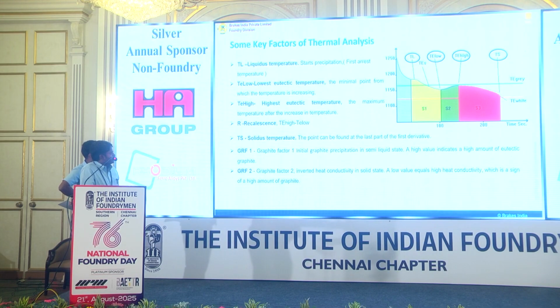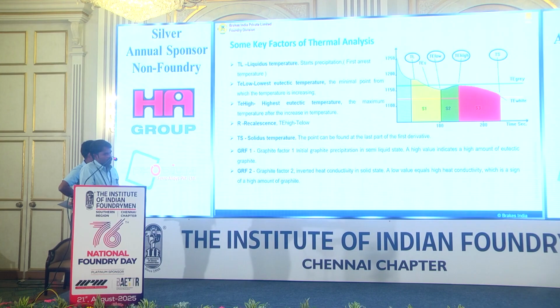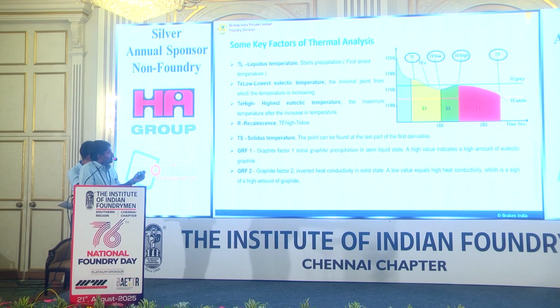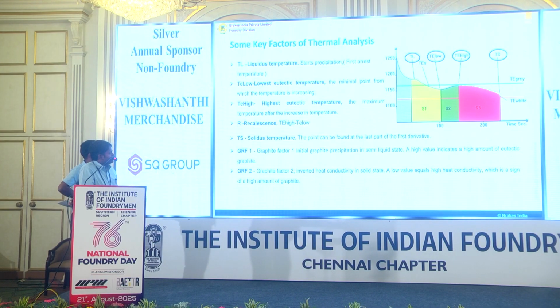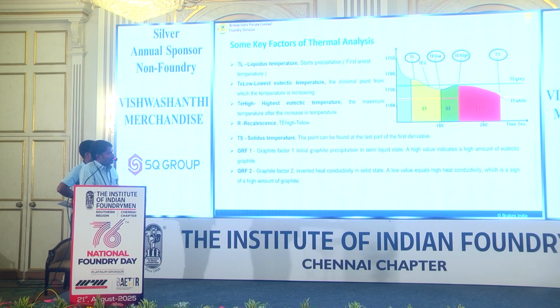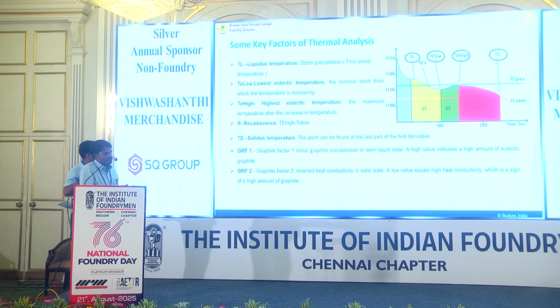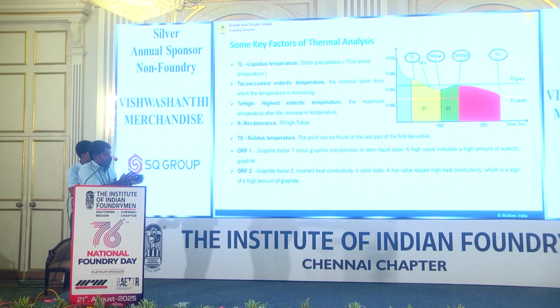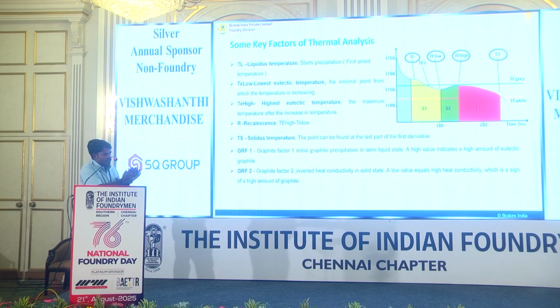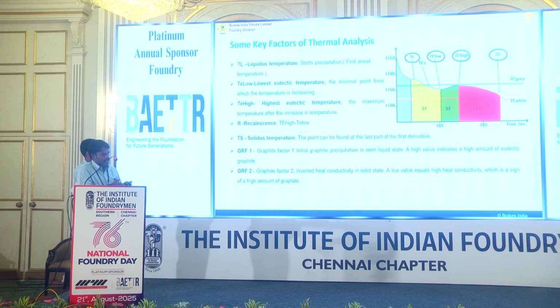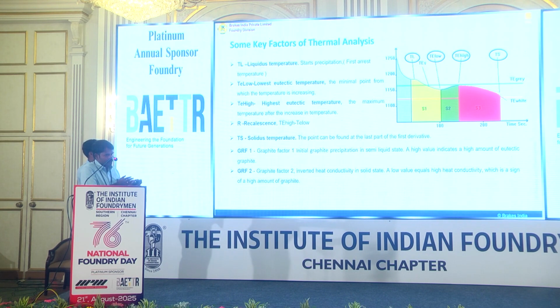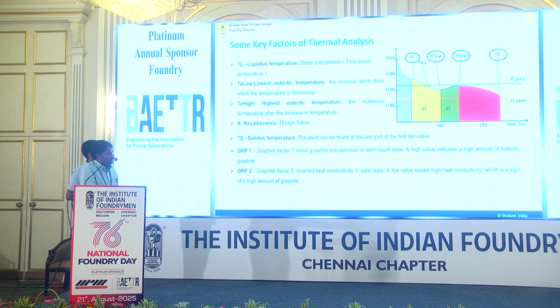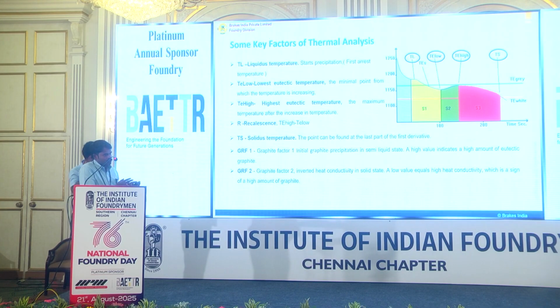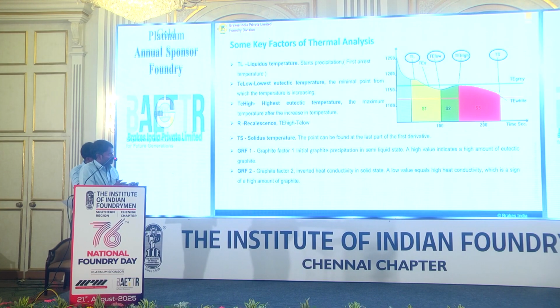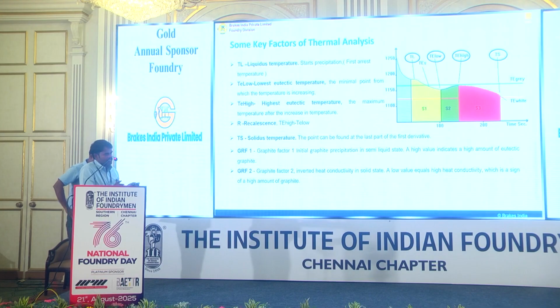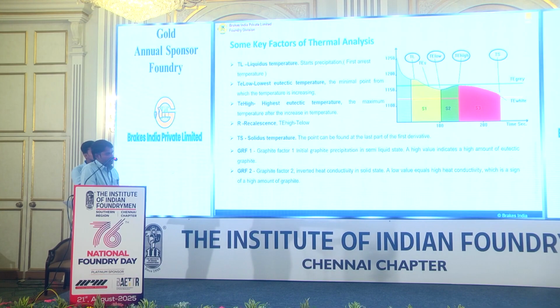So in between, two precipitations are happening: the graphite factor 1 and the graphite factor 2. Graphite factor 1 happens at the liquid to semi-liquid stage, that is, when the metal transforms from liquid to solid or semi-solid, the graphite precipitation happens. So higher graphite precipitation at the liquid to solid or semi-solid transformation indicates a very good eutectic metal.